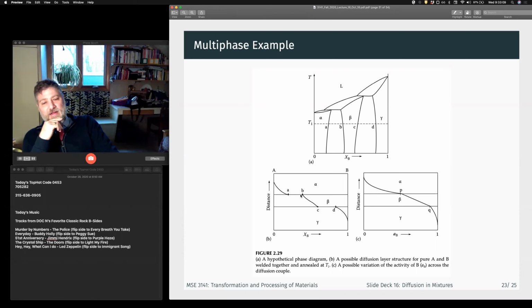So we have A, alpha, beta, and gamma are the only regions, the only phases that are going to be in our sample. What we don't see is the two-phase region here. So we move from one end of the sample where it starts at this composition, we move up in alpha, and then we hit an alpha beta interface where we have pure beta, and there's a step function in composition from A to B as we cross that interface.